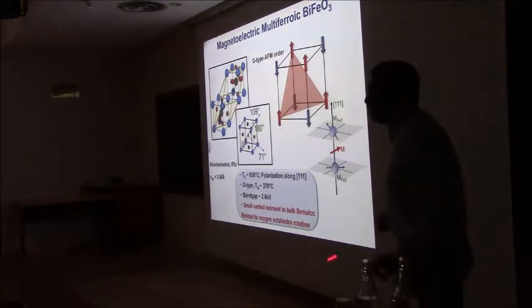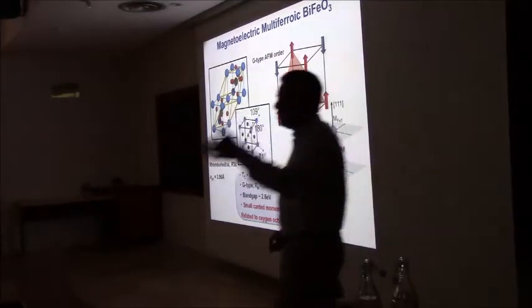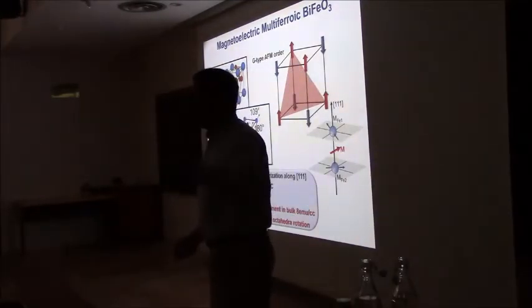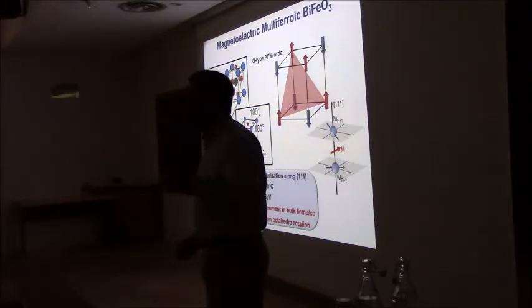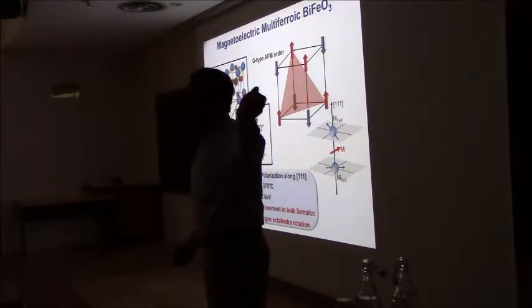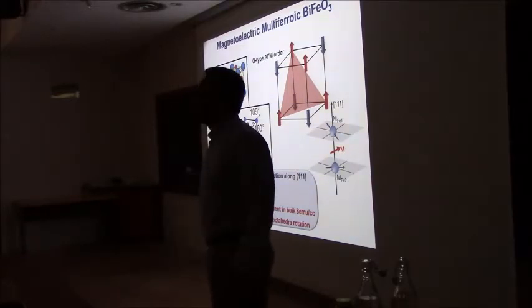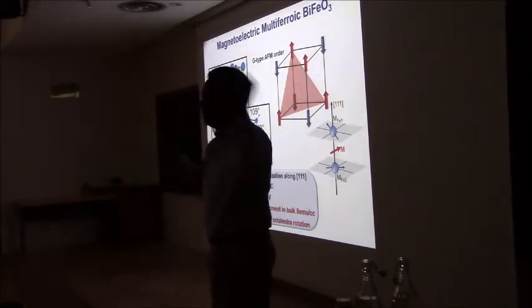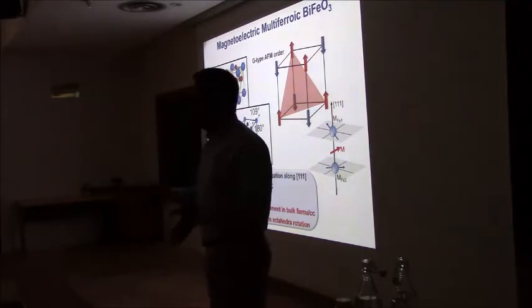There are a lot of things that I will not cover here, assuming that you've already heard. In the first 5 years, the biggest controversy was the polarization. When we measured it, we were getting polarization values of 90 microcoulombs per centimeter squared. The previous bulk value was 6 microcoulombs per centimeter squared. So the first 2-3 years, we were beating the crap out of each other, saying, oh, you're wrong, back and forth. It turns out it is indeed 90.